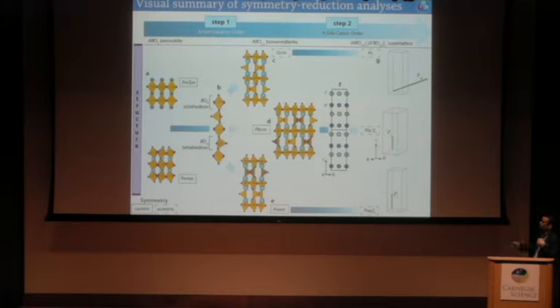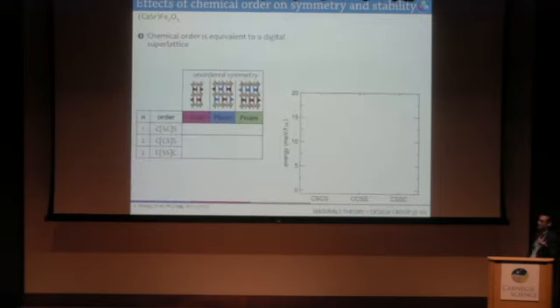So structurally, or visually, this is the design strategy. We start from perovskite, we add tilts, we add a tetrahedral, octahedral network, we add chemical order, and we can lift inversion symmetry. Okay. So what we want to do then is look at the stability of these phases from first principles. What I'll consider first, or if we can look at this compound now, calcium, strontium, iron 2 O 5. This is going to be a digitally ordered superlattice, if you want to think about it like that.